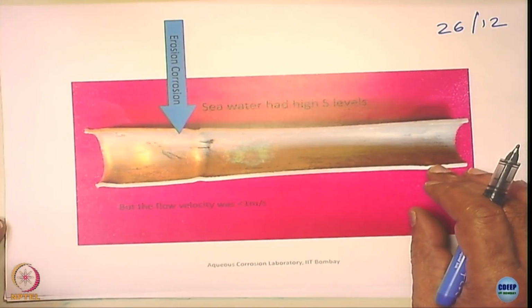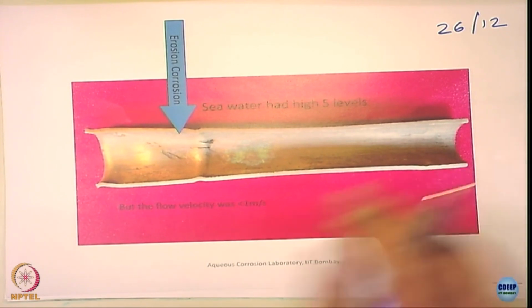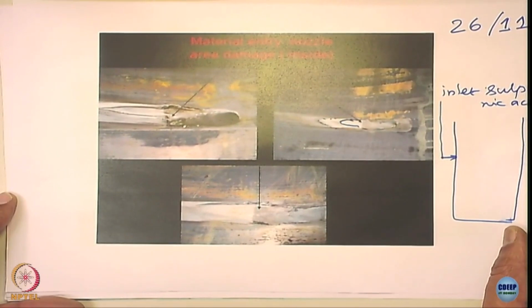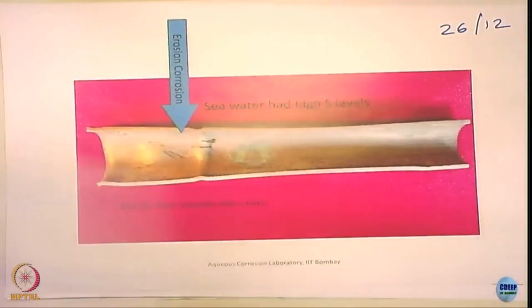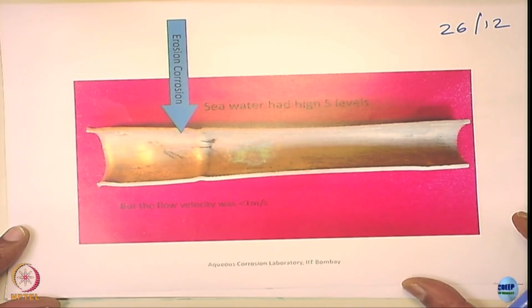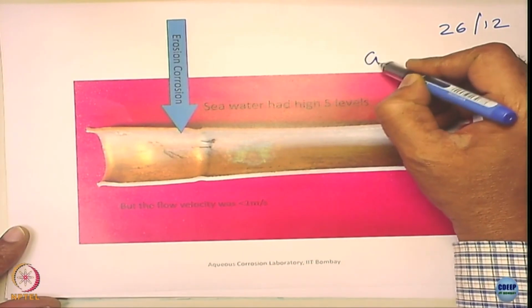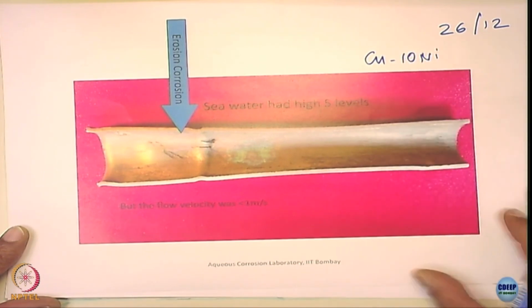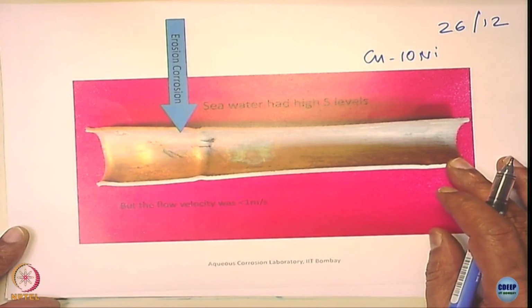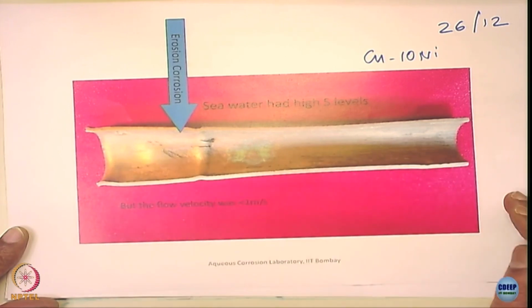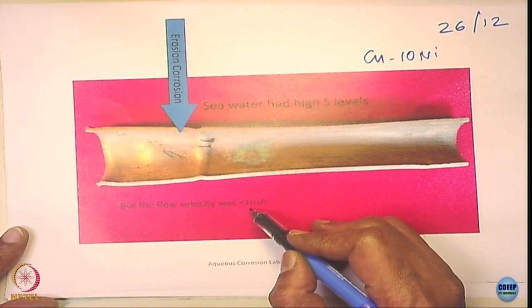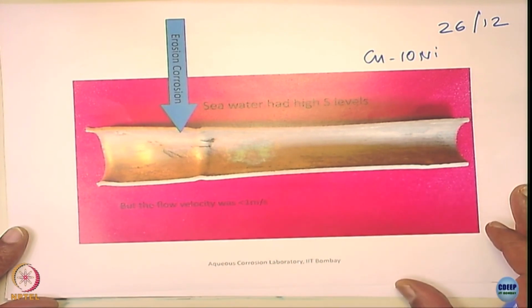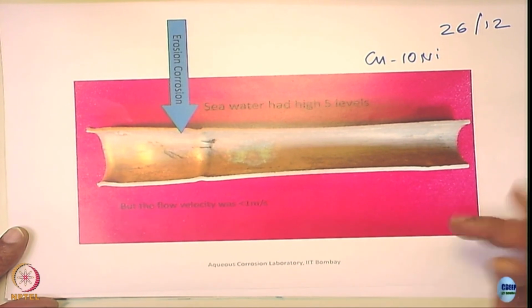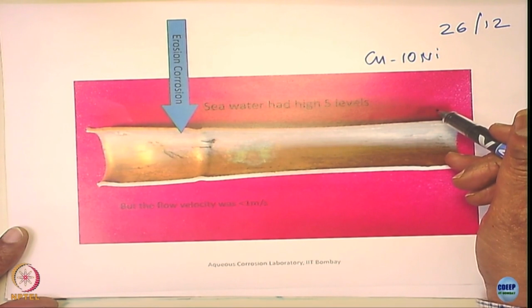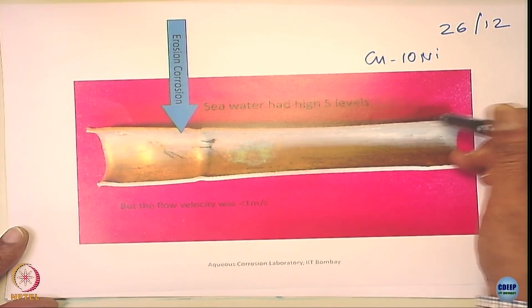The earlier one was a stainless steel. What you see here is not a carbon steel, it's a stainless steel. This one is a copper nickel alloy, copper 10% nickel, and this is a tube for a heat exchanger. In the tube the seawater was flowing. Look at this, the velocity was hardly about 1 meter per second. On the shell side, the process fluid is essentially hydrocarbon. You do not see any corrosion on the shell side.